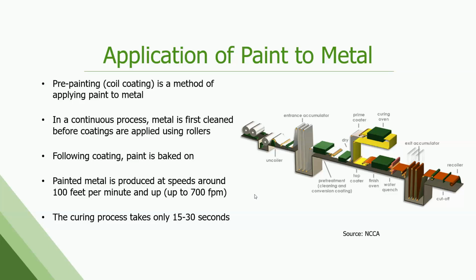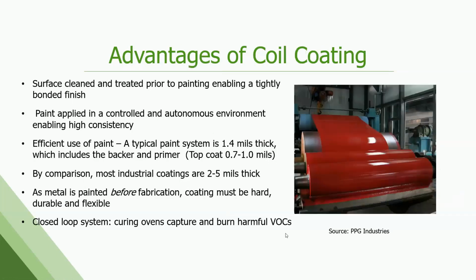These lines run anywhere from 100 to 700 feet per minute. From the time the paint is applied till fully cured and you're able to wrap that coil back up, it can be as little as 15 to 30 seconds. So very fast, very dynamic. But this allows us to have a very good, consistent product as well. Right? So it's highly controlled.